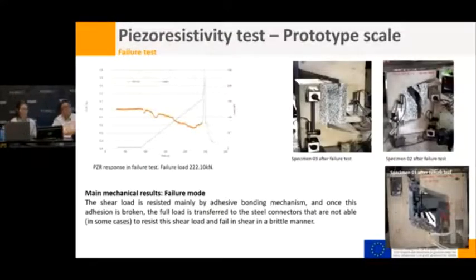And for finishing, this is a failure test performance. Here, as you can see, the fractional change in resistivity signal decreases as the conductive additives get closer, until here, where the lowering tendency stopped and increased a little bit, warning us that something is going to happen. The conductive pathways are cracking and now the conductivity is reducing. And then you can see here the crack, the failure.